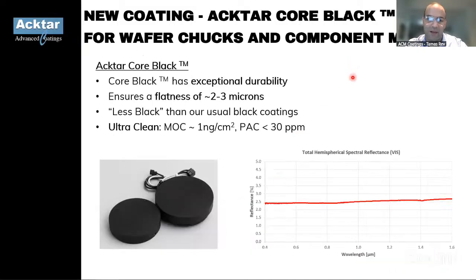So with that in mind, we have designed Core Black, which has exceptional durability. It ensures a flatness of about 2-3 microns on the surface of the coating. Generally speaking, it is less black than our usual black coatings, but it also possesses an ultra high cleanliness level. Molecular contamination would be about 1 nanogram per square centimeter, and the PAC value would be below 30 ppm. What you see here is the actual total hemispherical reflectance average graph in the visible range. You can see between 0.4 and 1.6 microns the optical performance of this coating.